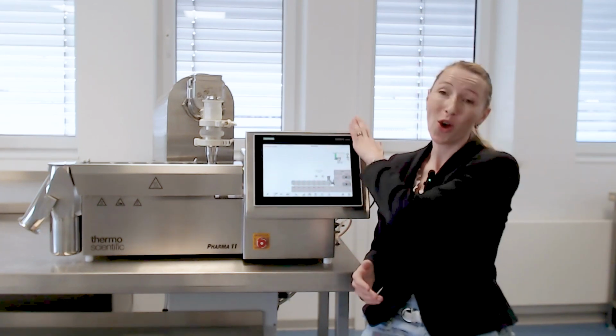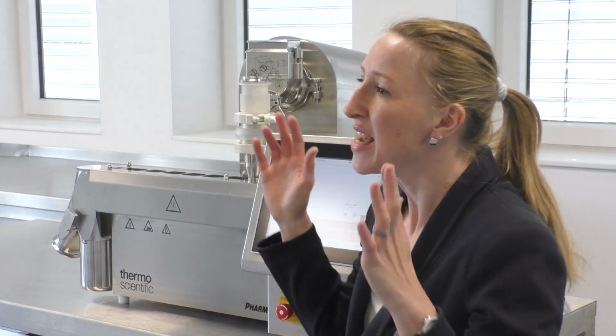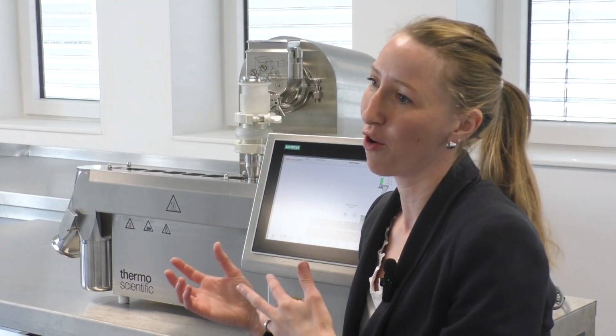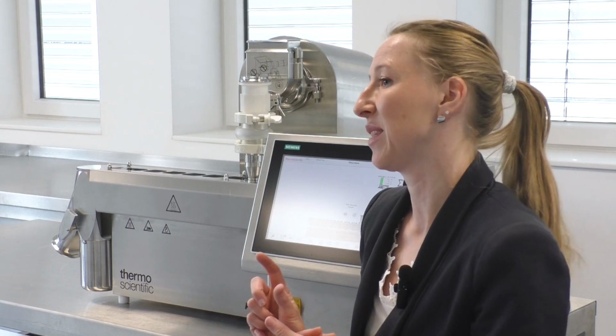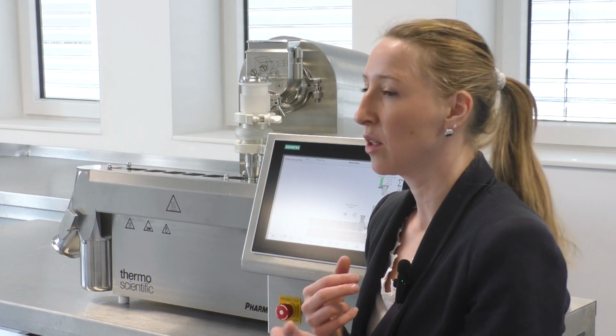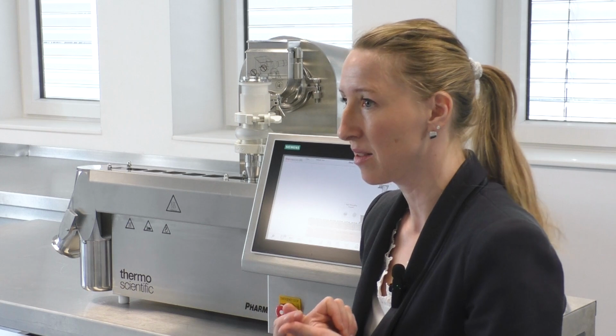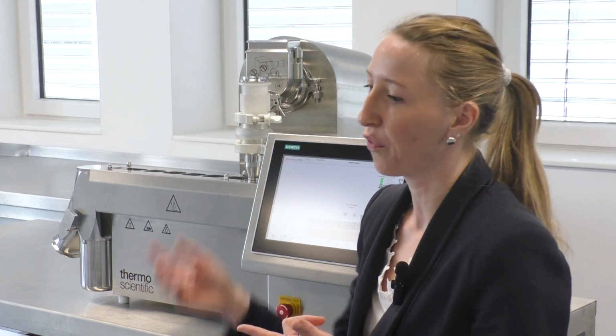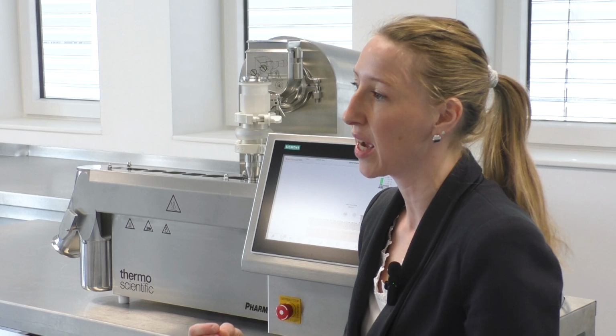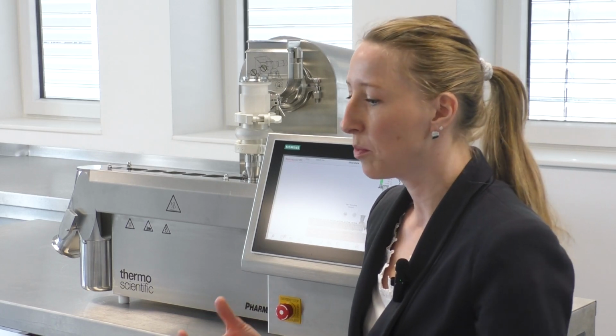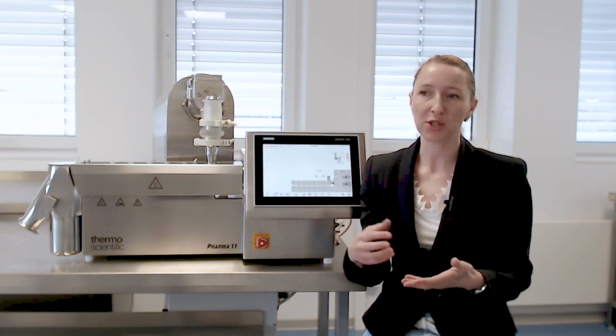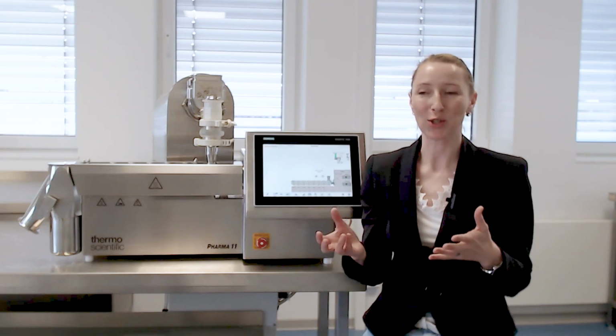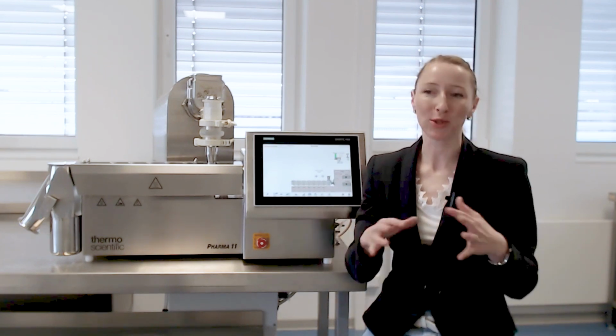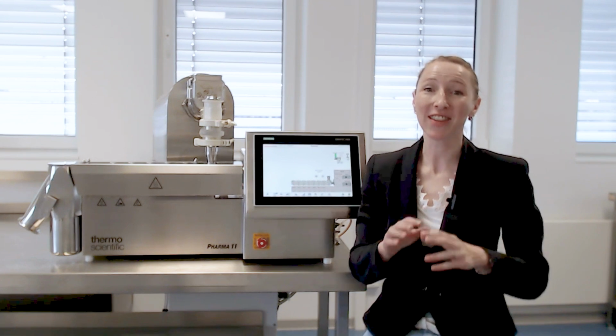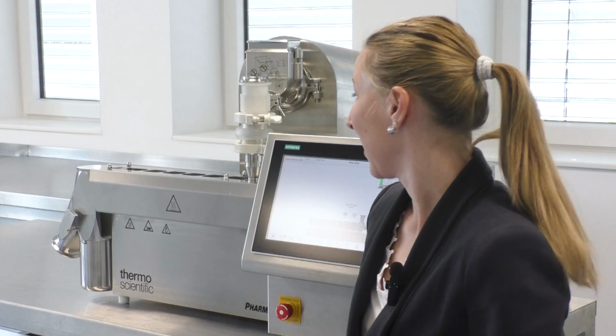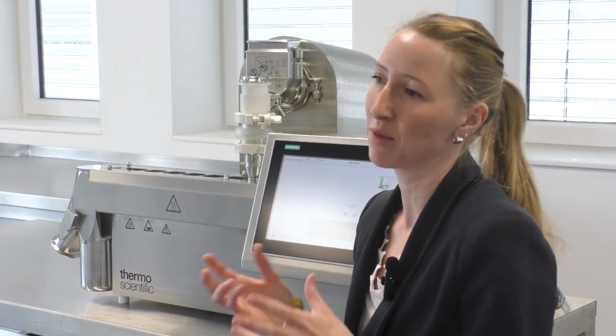Then you can also work with hot melt extrusion. So hot melt extrusion makes it possible to also make a drug amorphous. But there also we have some risks, because you need to melt the excipient, and you need to dissolve the active ingredient inside of this excipient. So it has to be stable at higher temperatures. You need to make sure there's no breakage of molecules, so everything is still in the shape you want to have it. So that's also something that makes it sometimes complicated.